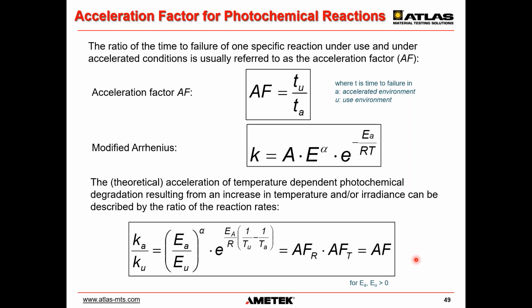caused by, actually, if you go down into specifics, the Franck-Condon principle, which says that the photophysical steps are independent from temperature because they are running on completely different time scales. And translation and vibration seem to be frozen when you are looking at a transition of energy in the electronic states of the molecule or the energy levels.